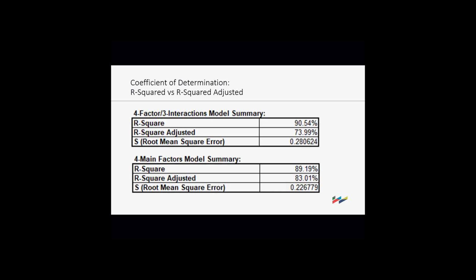And so here gives a sense of a 4-factor model where I include the 3 interactions. And you see that the R² at the top one is 90.54. The 4 main factor one is 89%. But look what it did for R² adjusted. So what this is telling me is that interactions are not a big deal with this process, at least this particular one.